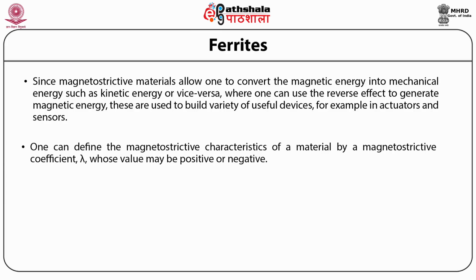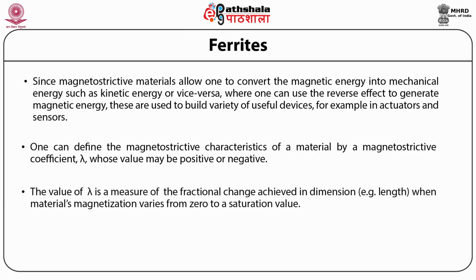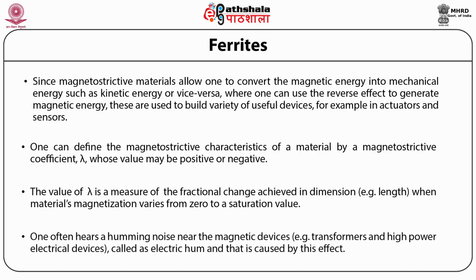One can define the magnetostrictive characteristics of a material by a magnetostrictive coefficient, that is lambda, whose value may be positive or negative. The value of lambda is a measure of the fractional change achieved in dimension, for example length, when the material's magnetization varies from 0 to a saturation value. One often hears a humming noise near magnetic devices, for example, transformers and high power electrical devices, called electric hum, which is caused by this effect only.